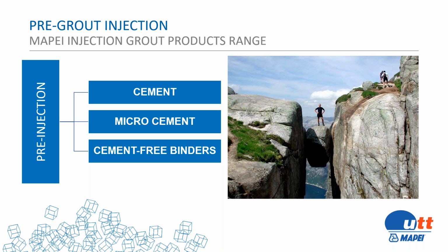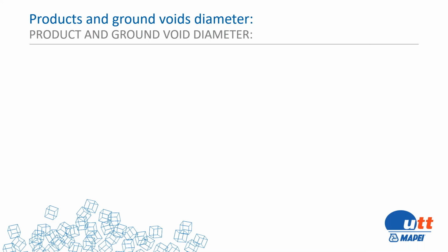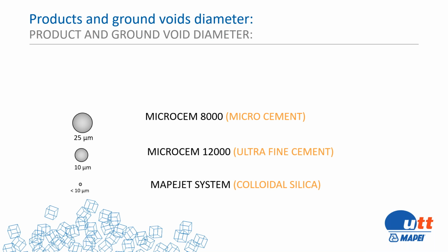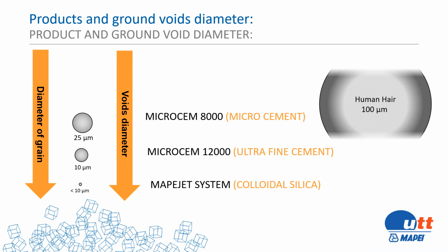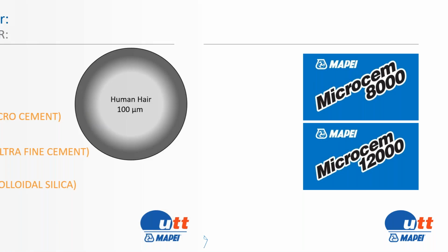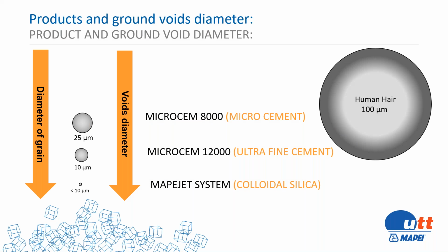So at Mapei UTT, we offer the microfine cements and the cement-free binders. When we look at the grain size and the void diameters in this chart, on the very bottom we have our Mapejet system, which is a colloidal silica. Then our Microcem 12,000 is an ultrafine cement, and then our Microcem 8,000. So what you have is grain sizes. If you compare it in size to a human hair, you can see that a strand of human hair compared to our microfine cement makes it very, very low viscosity and gives it great pumpability.